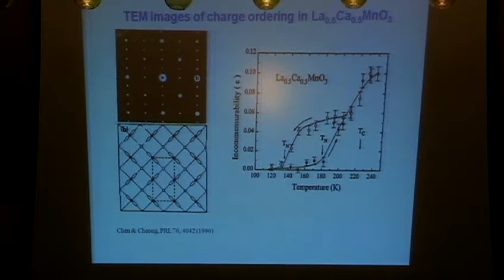Of course, when you warm up this charge-ordered phase, eventually there should be some point where the charge melts, and there will be a transition into something where the average order goes away. And how does that ordering happen? Well, it happens in a rather surprising way. What actually happens is that it goes incommensurate.